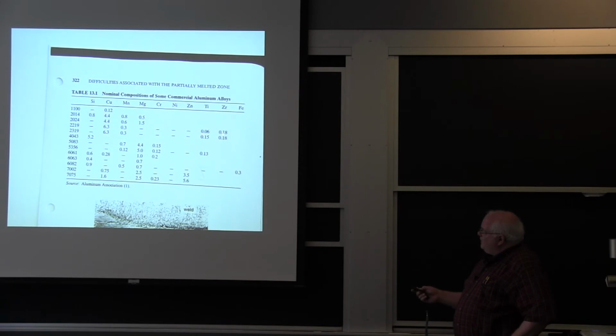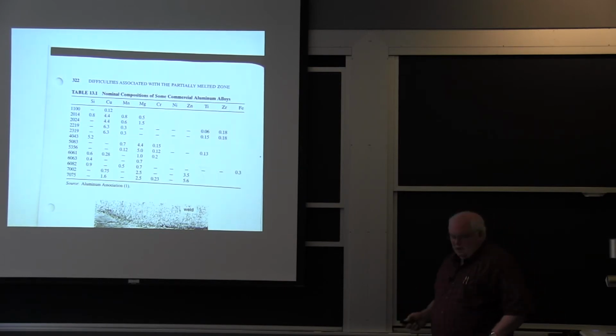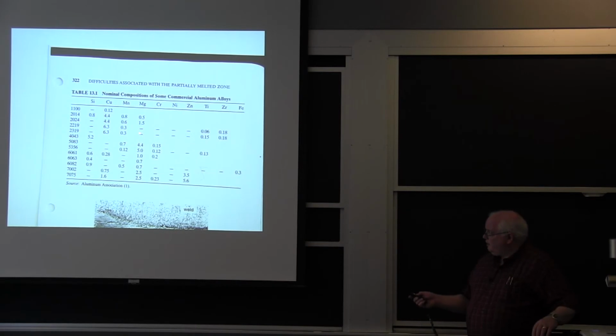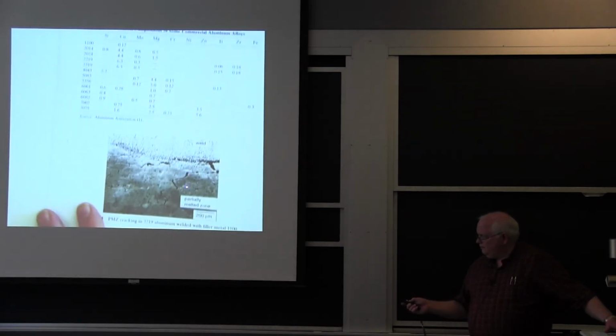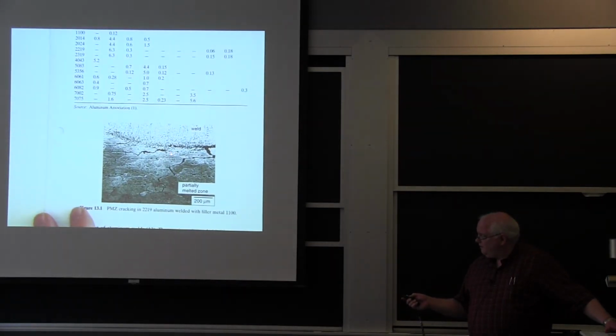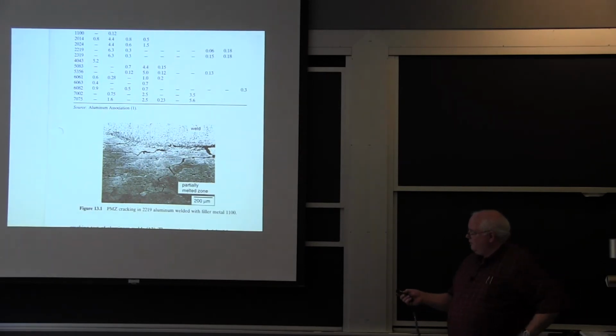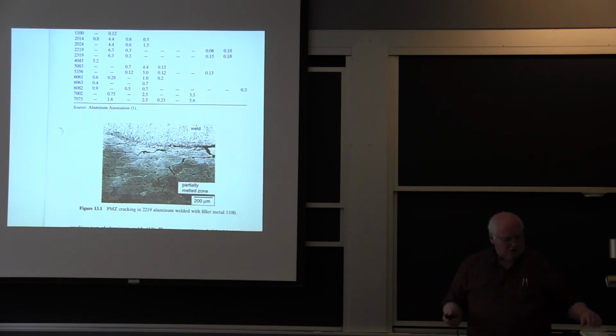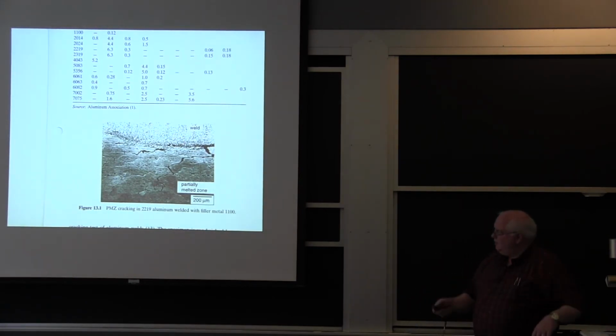Some of these have titanium or zirconium for grain refinement, similar to scandium, but scandium is more effective but more expensive so far as that goes. But the problem is, we talked about liquation cracking when you get a liquid up there yesterday, and this is actually 2219. So this is what they used to make the space shuttle great big external expendable tank out of.